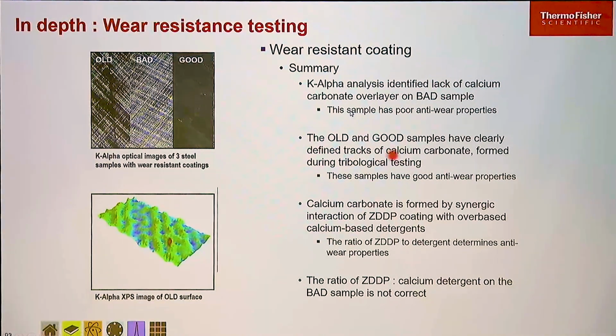So with clearly defined tracks of calcium carbonate being formed during the wear testing, we get good performance. If that isn't there, and that ratio of ZDDP to calcium detergent isn't correct, we get bad performance and we don't see the right wear characteristics on the part. And so again, detecting these very thin layers, remember we're looking at less than 10 nanometers of calcium carbonate on the surface, is determining the performance of this part once you've actually got it working in an environment where it's going to wear.